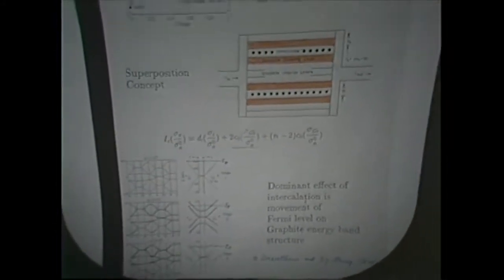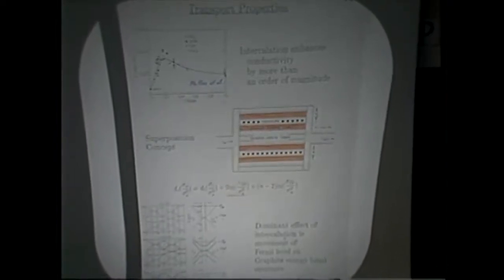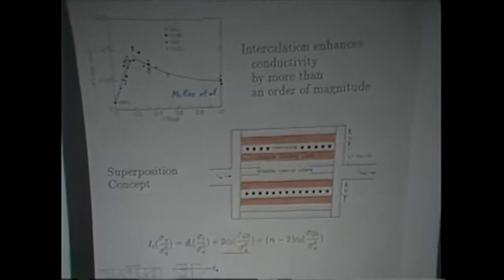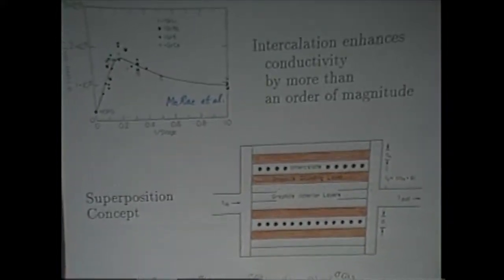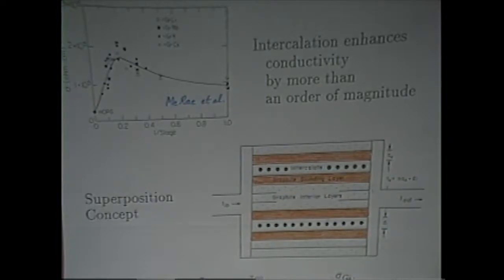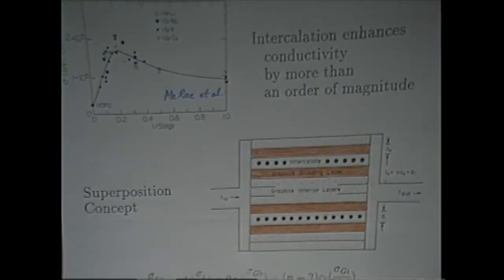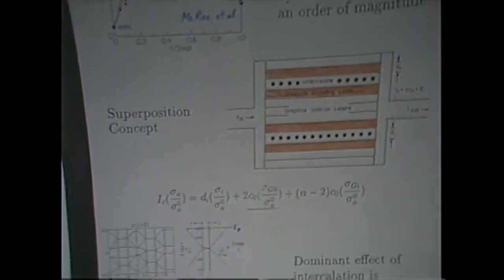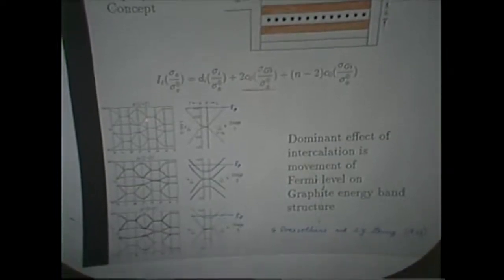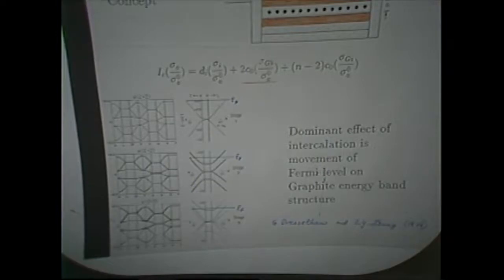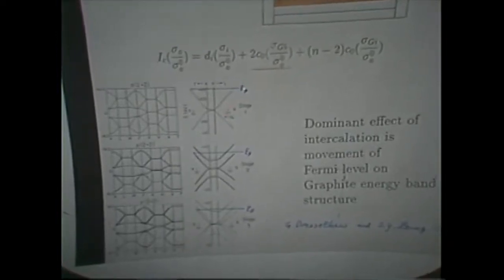Well, we could also understand from this model, not much intelligence needed, that the dominant important layers in graphite as far as transport are concerned are the graphite bounding layers. And to maximize the conductivity, you want the largest fraction of the sandwich to be graphite bounding layers. That tells you want to make a low stage compound, but don't make it too small, because if you make it too small, then a large fraction of the sample will be taken up with intercalate layers, which don't contribute very much to conductivity. And just to remind you what I said, here are the graphitic layers just zone folded to make the different stages. And all that we're doing here is we're changing the position of the Fermi level as we go along, and that makes the difference between stage 1, stage 2, et cetera, for the different conductivities.